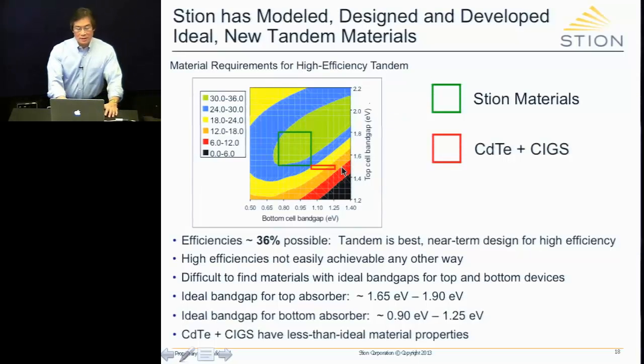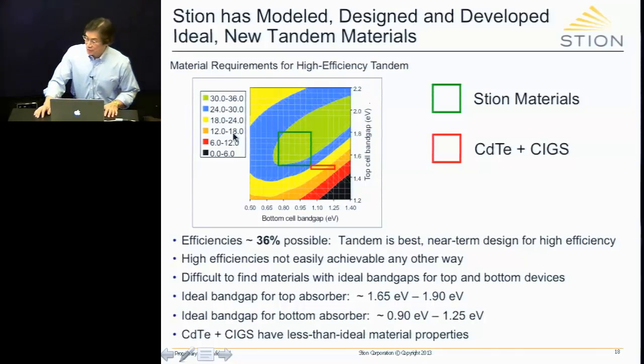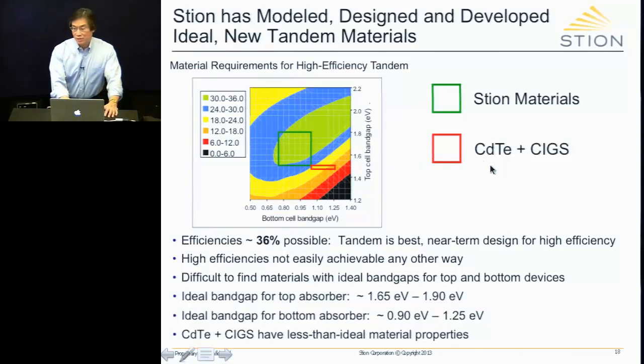So if you look at this, let's take the case that some of you had mentioned. That is using CIGS for the bottom and Telluride for the top. In this case, you would land right within this region right here. Okay. Now, is that good? Yes, it is. If you look at the yellow region, it is about 18 to 24%. Now, the thing to keep in mind is that with many calculations, oftentimes you can't get to the efficiencies given to you by the calculation. We feel that if we get to half of that, we're doing pretty well. So at 18 to 24, that would get you to 12%. So on face value, it seems pretty good, but in actuality, it's not as good as you want it to be. So that's with the CIGS and Telluride combination.